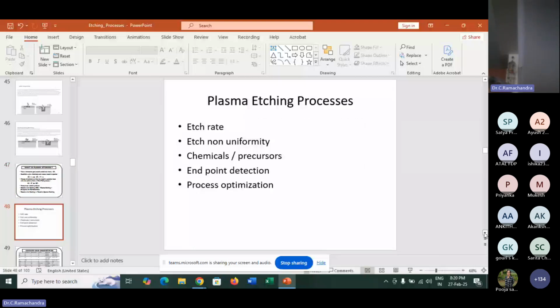So etch rate is important. Etch non-uniformity, typically my requirement is 5%, not more than that. Chemicals and precursors depend on what materials I'm going to use. Today we have a library of different precursors, and there is scope for developing new precursors which provide better performance. It's always welcome. Suppose today I am using CF4 for etching silicon. You can find some other chemicals, precursors, which give better results in terms of etch rate and particle contamination. There is scope. This is unlimited. And endpoint detection is important, particularly in a manufacturing environment, and process optimization for different materials. We need to develop the process and optimize it.